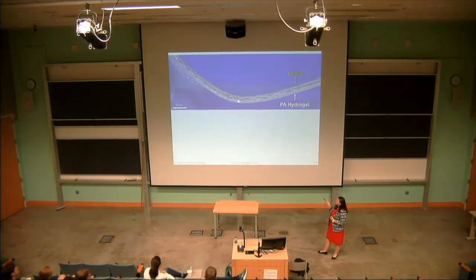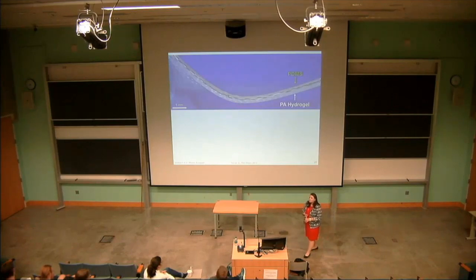Here in the center, you're gonna see this little cross-hatching there. And that cross-hatching is actually a glass fiber fabric material. It's just an E-glass weave textile. It's about 0.6 millimeters in thickness, and each one of these gel layers is 1 millimeter in thickness on both the top and on the bottom. So this project had two main goals, first of which was generate the composite structures. So there was a system in place where they've been making these fabric-reinforced composite materials, but they've never combined two materials with the fabric. So that was the first goal of the project. The second goal was to apply stimuli responsiveness, right, to make them move.